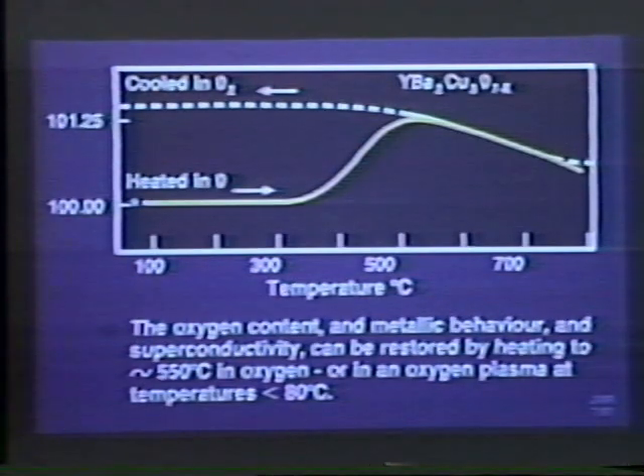All you have to do is heat the material in oxygen, and you can see this is the weight against temperature. Starting at the lower left corner, as you heat the material, the weight begins to increase at a little over 300 degrees, increases to a maximum at a little over 500. Then as you cool it slowly, the dashed line, it picks up a little more oxygen as you cool and has optimum properties by the time you've cooled slowly down to room temperature.